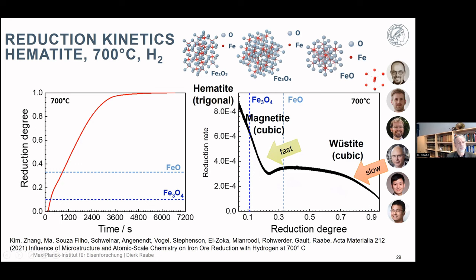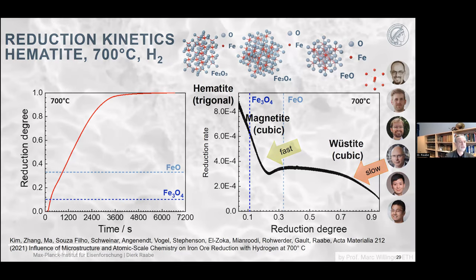But you see from this diagram, in principle, the take-home message is that you lose one order of magnitude in terms of the reduction kinetics. That is, in other words, a very slow process, and that is, again, in steel problematic. Because you remember, when you do something in steel, it must be scalable to about 2 to 3 billion tons per year. That means you must have fast reactions.